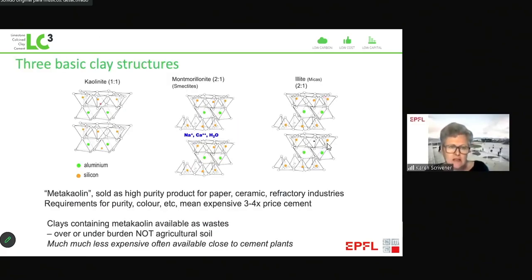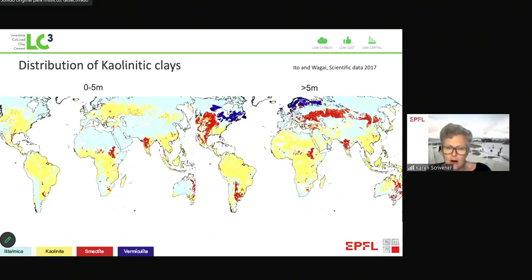And the reason kaolin is so interesting is because it has this so-called one-to-one structure where we have a layer of silicates and a layer of alumina, and during the calcination process this crystal structure becomes disrupted and both the silica and alumina are available to react. And the alumina is the alumina content that reacts with the limestone in this synergetic reaction. And these kind of clays are really very widely available.